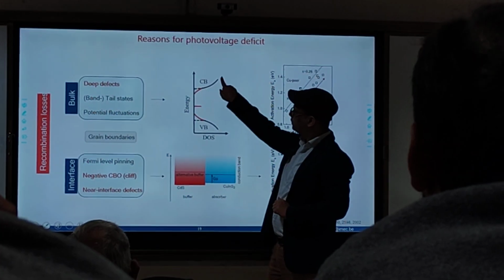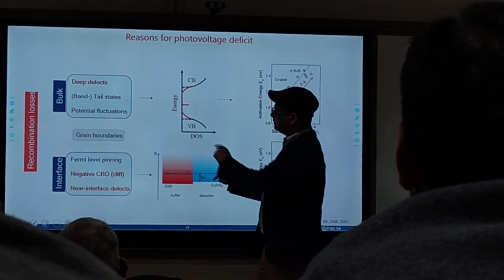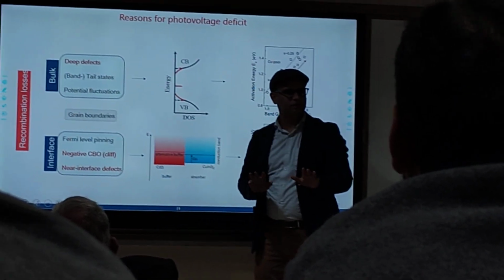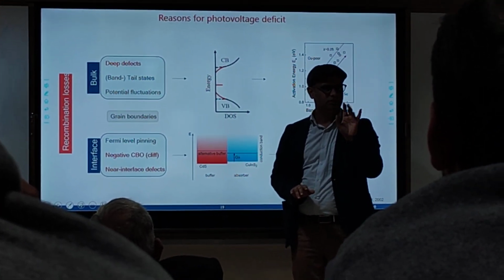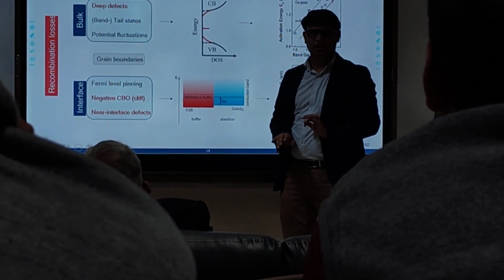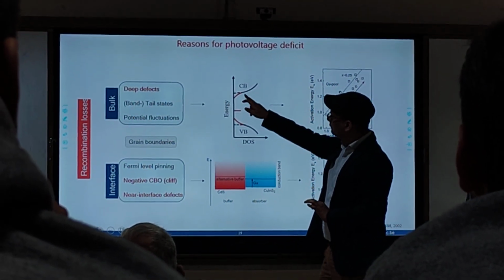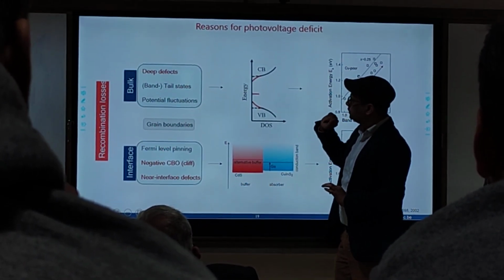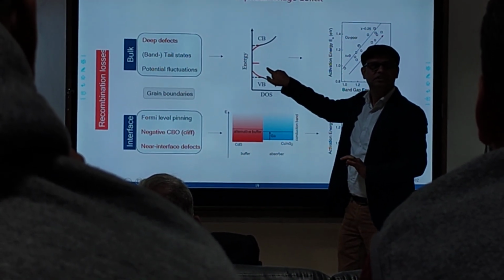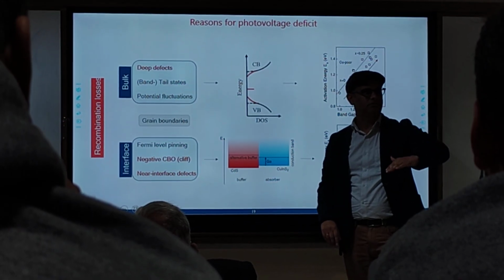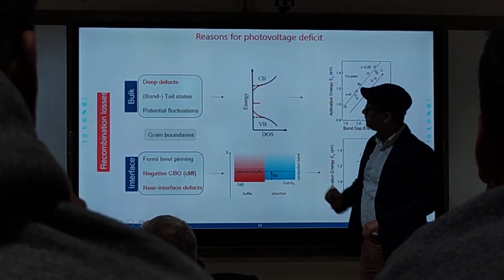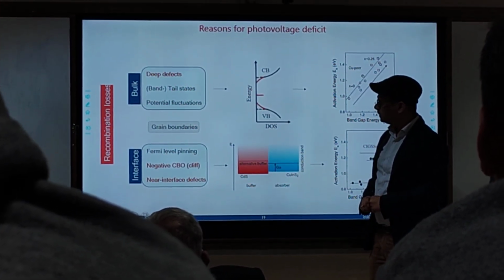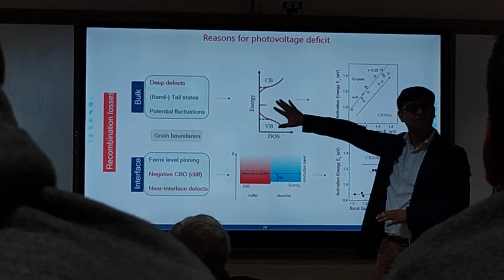You can have this, more or less, conduction band, valence band. These red things are the tail states because of the disorder. Okay? These are like very low density of states, let's call it. So above tail, you can have recombination from these tails. You can have a recombination through this defect which is somewhere in between, which is a deep defect, right? So all the carriers just can come and relax here, and you lose those carriers. So these are more or less bulk recombination.